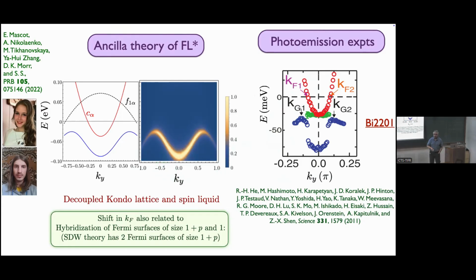Yes? Within this model, why is there an anisotropic spectral weight? It simply comes from the hybridization. So in fact, this is near the nodal point, but it's similar near the antinodal point. The original one is near the nodal point. You have the top layer, which is the C band, and then you have the F1 band. And the front side is mostly C, and the back side is mostly F. So that's why it comes. It's also present in spin density wave theory.